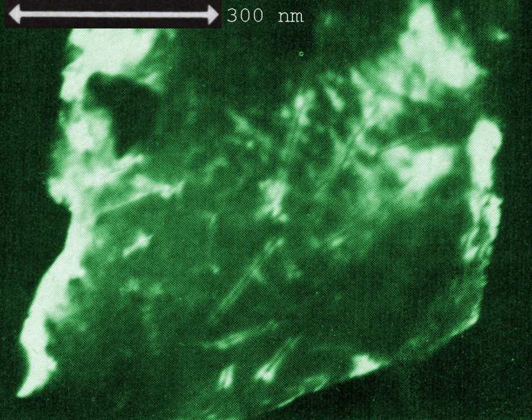Low atomic mobility. For selective ion track etching, the density contrast between the latent ion track and the pristine material must be high. The contrast fades due to diffusion, depending on the atomic mobility. Ion tracks can be annealed. Erasing is faster in glasses compared to ionic crystals.